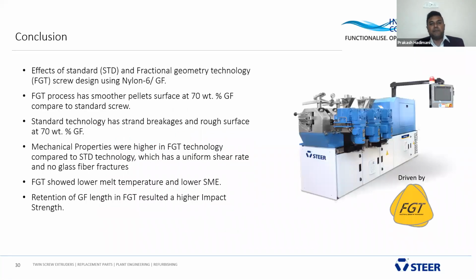Next person. And finally, we conclude. Okay, we have studied the effect of standard and fractional geometry technology using TSE with nylon 6 and glass fiber, with the filling concentration increased from 60 to 70%, 60, 65, and 70% weight percent. Okay, FGT technology shows a smoother strand surface compared to the standard. But in standard technology, the fibers came out from the surface. So that shows the wetting was very poor.